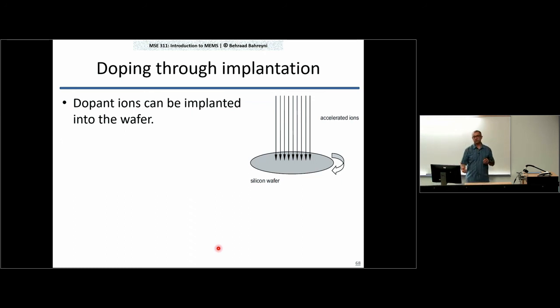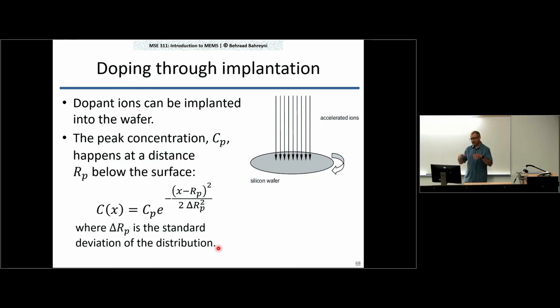It's going to go, let's say, 100 nanometers, 200 nanometers, or a micron or two, and then they stop. They are stopped by the crystal that you're shooting them towards. They don't have that much energy to go through the substrate. But nonetheless, if you manage the time, the dosage, and the energy of these ions, you have a lot of control over the profile that you want to get and the concentration that you want to get.